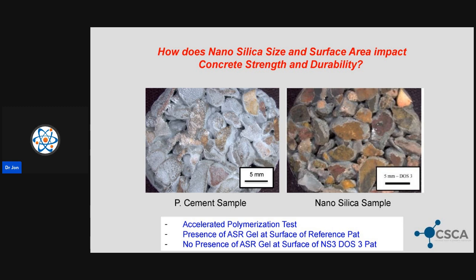You're taking your aggregate, grinding, grading, and washing it to a 1 to 2 millimeter gradation. And then you are putting it in a very thin paste, almost like a pervious mix, curing it for a 72-hour period, grinding the top paste off, and then from there, putting it into a pore water solution for 72 hours at, I believe it was 125 degrees Fahrenheit, somewhere around there. And what you do is first, it's an accelerated polymerization test.